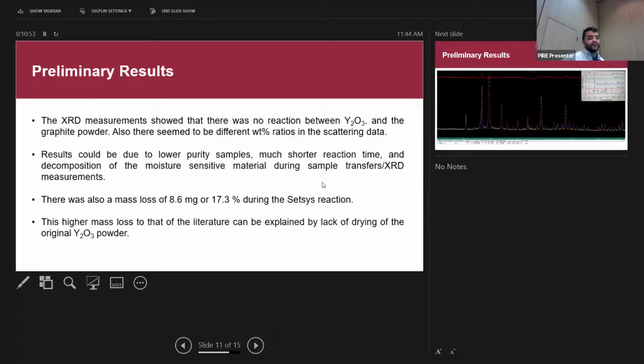So in the preliminary results, the XRD measurements showed that there was no reaction between the Y2O3 and the graphite powder. And also there seemed to be different weight percentages in the scattering data. I will show that in the later slides. I just wanted to put the conclusion first. The results could be due to lower purity samples, much shorter reaction time, and the decomposition of the moisture-sensitive materials during the sample transfer and XRD measurements.